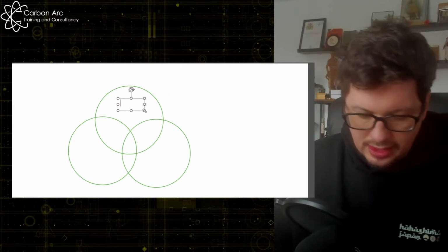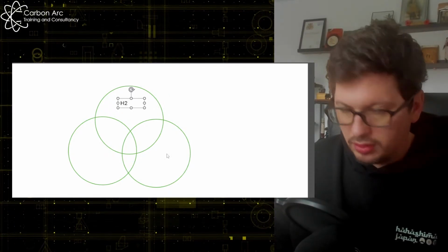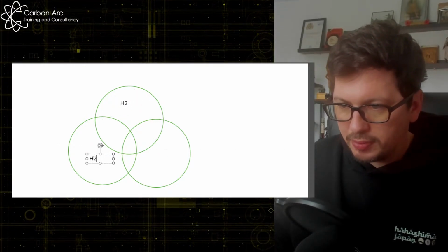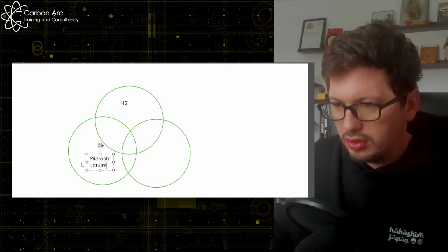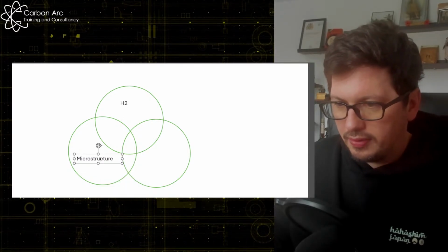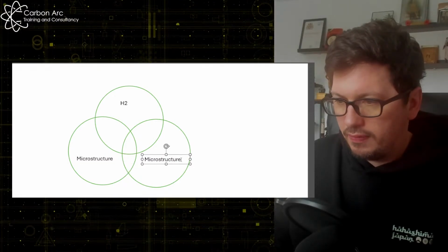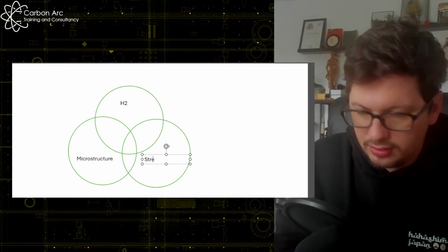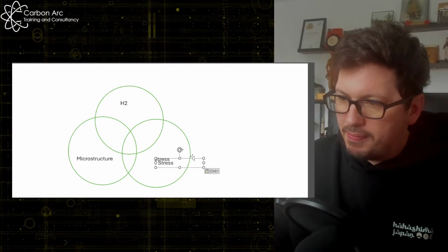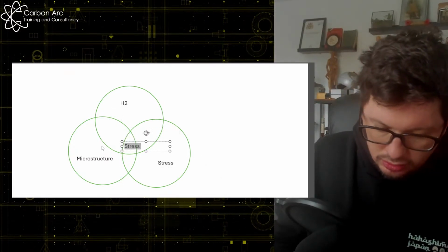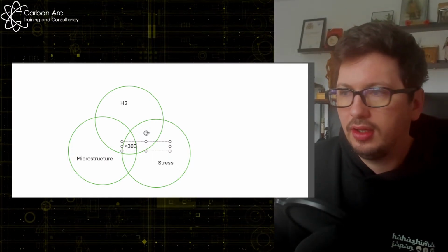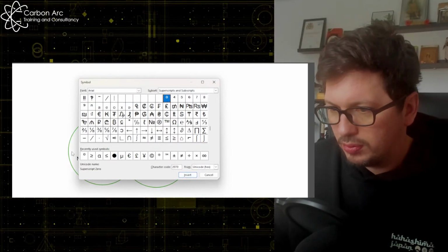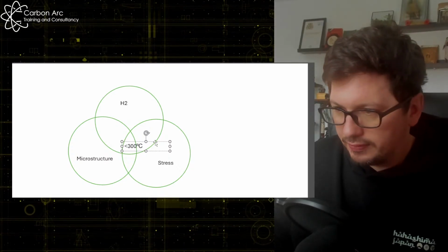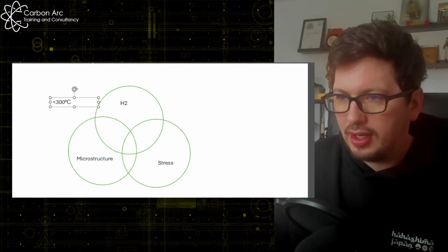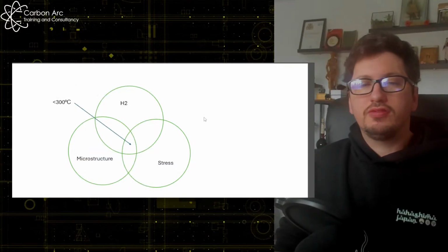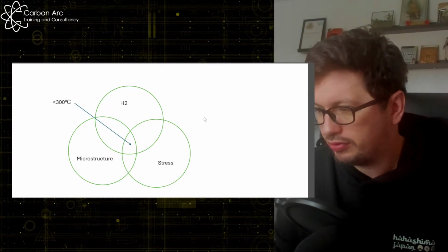Okay, so we need a hydrogen level, we need a microstructure which is susceptible to cracking. Right, typing fast. And then we need our stress. Right, and then in the middle, this is a temperature which is below 300 degrees Celsius. Okay, let's insert a proper symbol into that. Degrees C. Now I normally just put it out here and then stick an arrow in to say right in there. We say 3 things, but really it's 4, isn't it? Because it has to happen under 300 degrees, right?